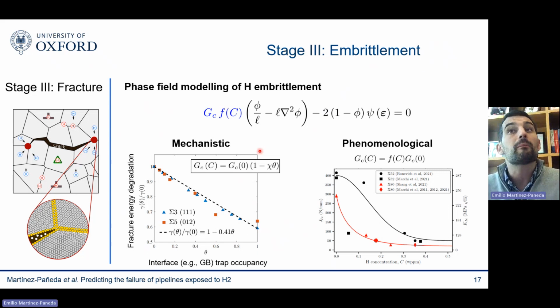fracture energy. But most often when we work with our industrial partners, we look for this phenomenological or empirical approach, because this is useful if you don't know anything about your material, but most often we're dealing, like here, with pipeline steels, where we have plenty of toughness versus hydrogen content data. You can see here, toughness, fracture energy versus hydrogen content. You can see there's plenty of data. This is from Sandia, I think. Most of the data is from Sandia, X80 and X52. So we can fit that data with a polynomial and introduce it directly into our model.